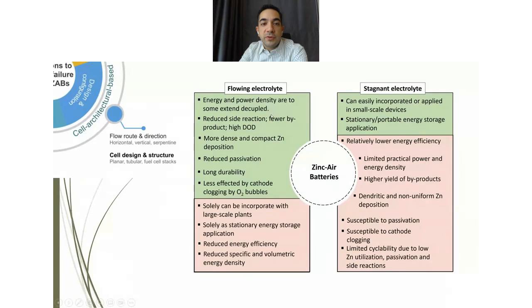Also, we can operate at a higher depth of discharge. The morphology of zinc will be compact and dense, and the passivation layer can affect the system less when the electrolyte is flowing. So the battery has longer durability, but the negative aspects are that they usually are suitable for large scale plants and they cannot be applied in portable batteries and devices. And also, they have reduced energy efficiency.